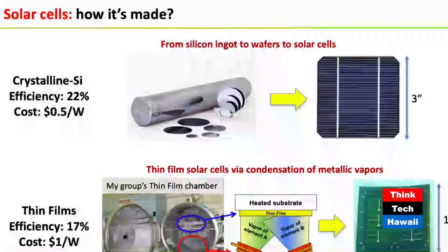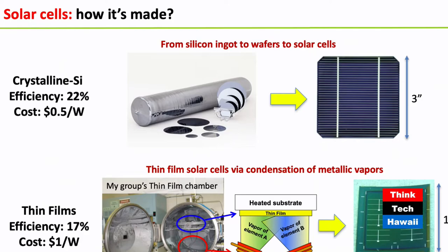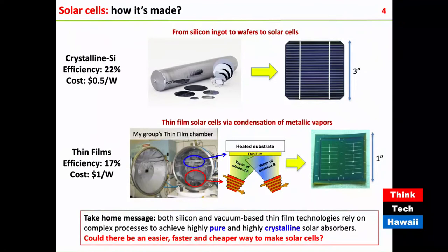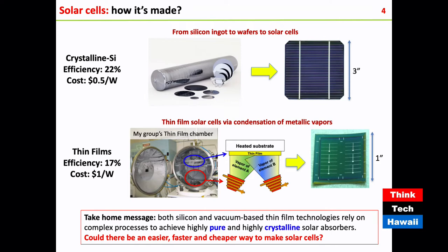So just by pulling, if you want to show the slide again, that very big salami of silicon was actually hanging from the left-hand side. You have a little tip. A little tip there, and it was pulled very slowly from the silicon melt. Making an ingot like that takes about 3 to 4 weeks. So it uses a lot of energy too. It does. It takes thousands of degrees. You're melting glass. Exactly. Or melting sand. Exactly. 24/7 for 4 weeks. Right.